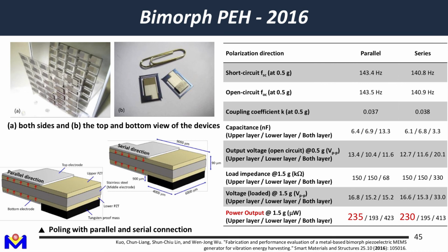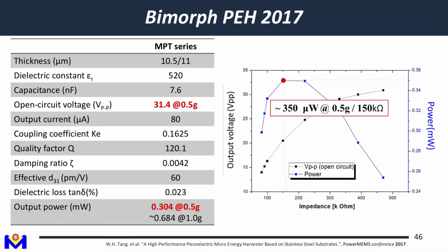For the two piezoelectric layers, it's also the same. You can choose a parallel connection or a series connection for higher voltage, lower current, or higher current, lower voltage. Okay, so this is the other optimization. We want to optimize the power output at a lower acceleration level. So in 2017, we did certain optimization so we could achieve around 350 microwatt at 0.5 G. Again, this does not mean this one is better than the previous one. It actually depends on what acceleration level you want to optimize, and that depends on your real application scenario.